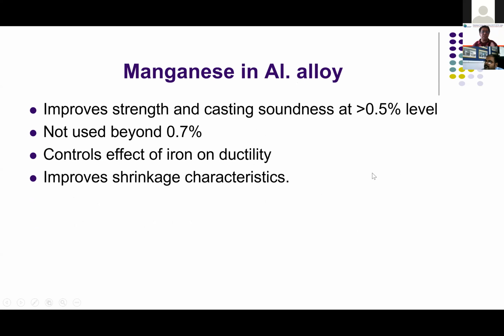Manganese in aluminum alloy. This manganese improves the strength and casting soundness. It is normally used below 0.5%. Definitely not above 0.7. We normally recommend half of iron. Suppose the iron is 0.7 or 0.8, I recommend 0.4% manganese. Because this controls the effect of iron on the silicon present. You see, iron always plays its part, spoil sport, in the silicon structure.